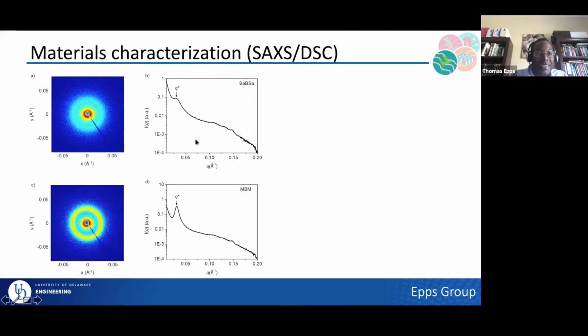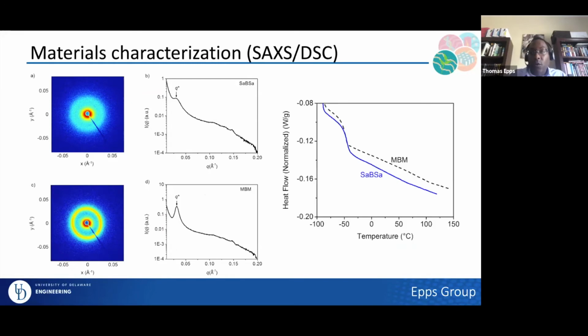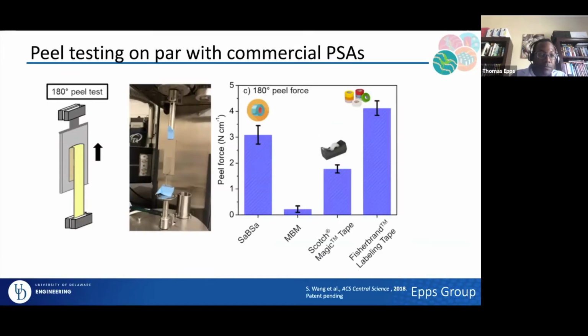But the point of showing this is that we actually have about the same domain spacing, we have the same composition. I'll show it here. We have the same glass transition temperature type behavior. And from TEM, which is not shown, we actually have the same spherical morphology. So we really think that we're making an apples to apples comparison to what I'm going to show next.